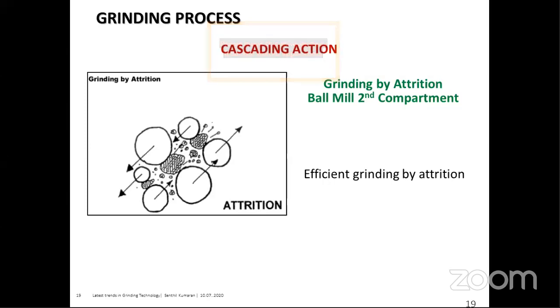After some size reduction, the material passes to the second compartment, where efficient grinding is done by attrition. As I said, the small size media, from 25 to 15 mm, rub against each other, and the material passes through attrition. This fine grinding occurs, and it grinds the material into a finer product.